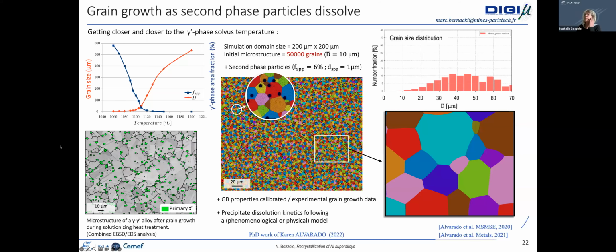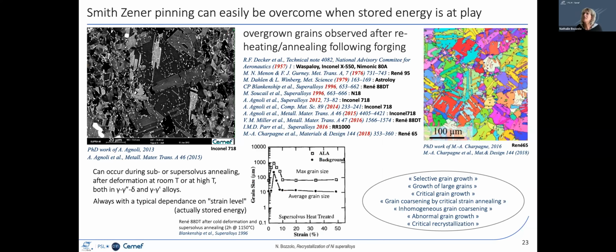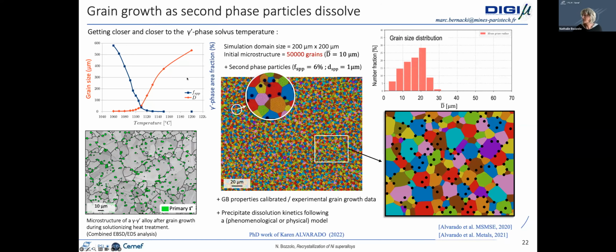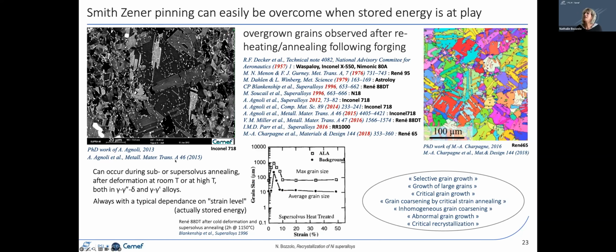But in some cases, you can find very large grains with many second phase particles inside the grains. I'm sorry, Evan. So this grain has very obviously grown despite the presence of the second phase particles. So this is an example in the Inconel 718 alloy, and here you have another example of a gamma-gamma prime alloy. So actually this has been observed in many different alloys.